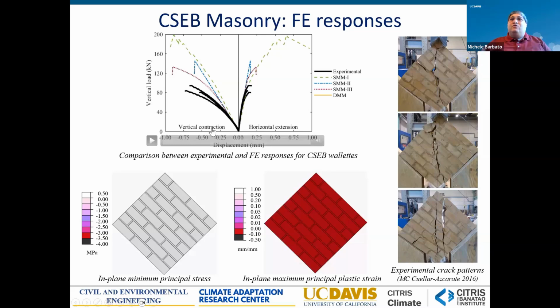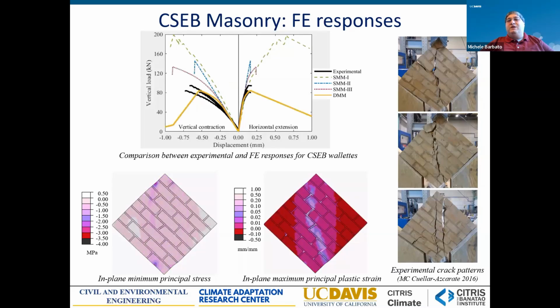So they are kind of consistent and they are significantly lower strength than the one estimated with these other curves. So at that point, we had a very strong indication that we needed to do something different. And the something different was developing this detailed micromodeling approach, which actually was able to capture both the global and the local behavior of this new masonry extremely well.